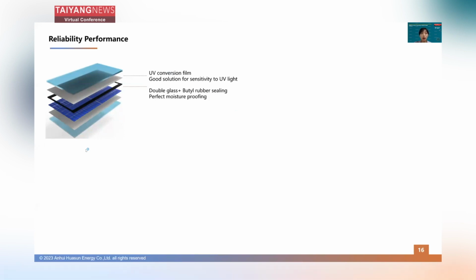And not only that, our Huasun company can also develop the best module encapsulation design specifically for the heterojunction cell structure. Because we all know that the heterojunction cell structure is sensitive to UV light and also the moisture environment. So Huasun has developed the UV conversion film, which is a good solution for the HJT cell sensitivity to UV light. Also, we applied the double glass with PIB sealing on the module edge, so that the HJT module can have better moisture proofing performance.